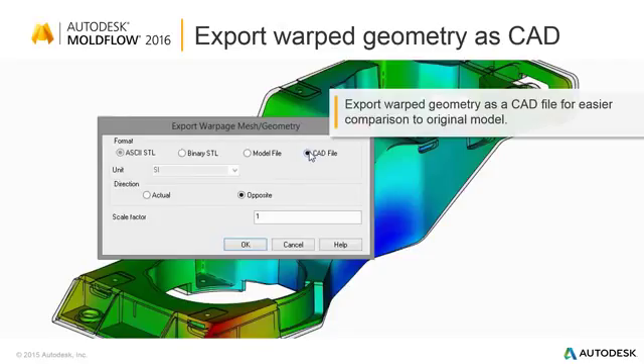So particularly for this last one, the warpage model, you would use the opposite over here. We typically don't see people using the full warpage, but let's say 70% of that particular warpage, because the actual deformation causes some extra structural stiffening of the part, if you will. So typically people don't apply the full opposite warpage, but a portion of it.